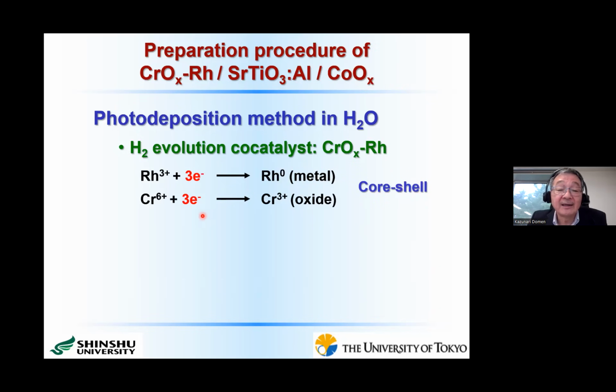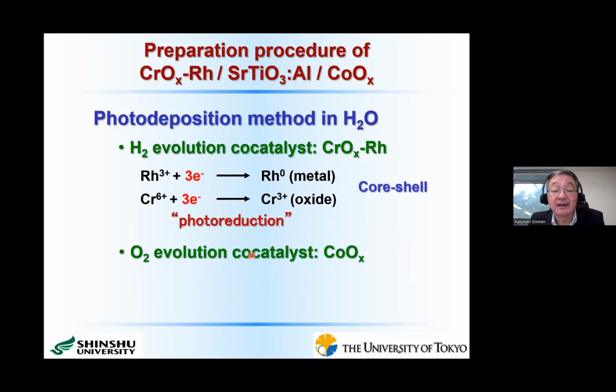But in any case, these two reactions use photoexcited electrons. So these two reactions are so-called photoreduction reactions. After that, we construct the oxygen evolution co-catalyst. That is cobalt oxide, cobalt oxyhydroxide. In this case, we use photoexcited holes to oxidize cobalt 2+ into cobalt 3+. So this reaction is actually a photo-oxidation reaction.